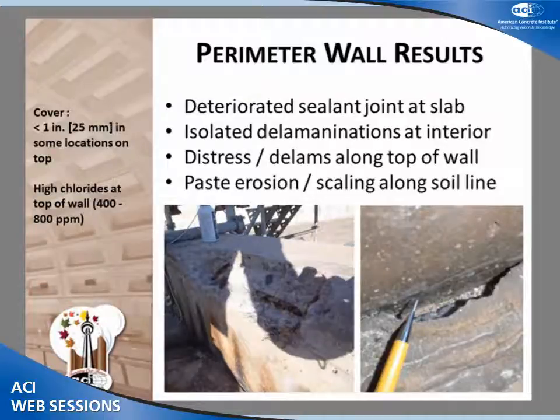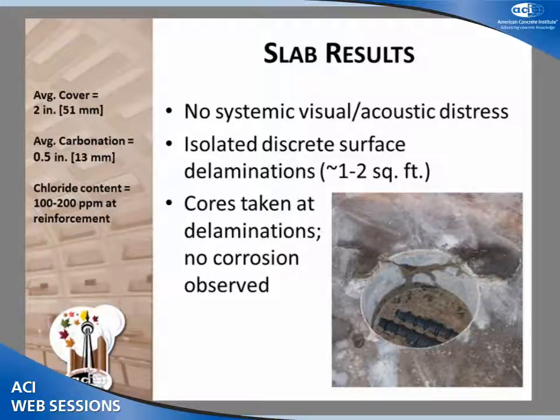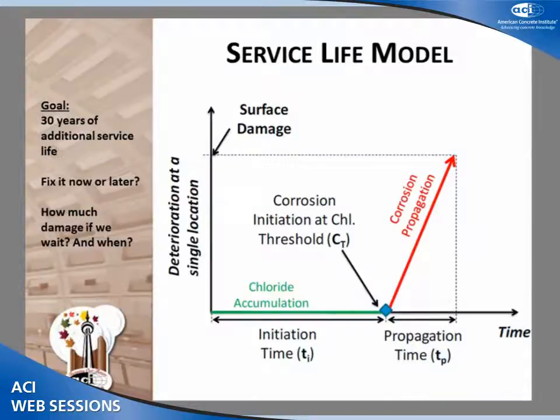At the top of the wall, we had high chlorides and about 30% to 40% of the wall top was either delaminated or, once we applied a hammer, it completely spalled off. The sealant joint, similar to the adjacent trickling filter, was in bad shape. For the slab, we had some local delaminations — not nearly as much cracking as seen on the adjacent trickling filter — and cores showed good cover depth and no ongoing corrosion, with low chloride levels.